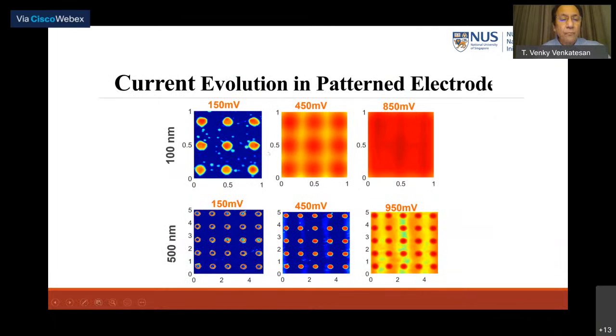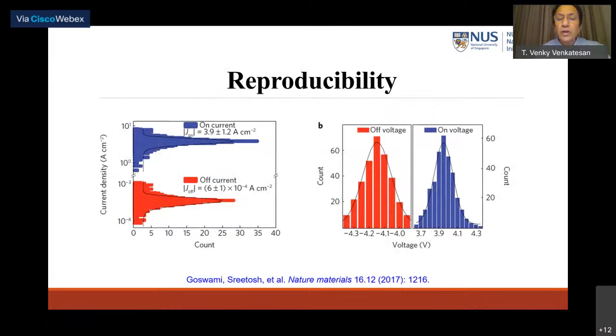Here, for example, are patterned bottom electrodes, and there's molecule everywhere. When we apply a conducting AFM tip and scan over it, you see that by 150 millivolts, this 100 nanometer dot is fully switched, whereas the region in between is not switched at all. What this tells us is that when we make these devices into nanostructures, and right now we've shown that we can get down to a size smaller than 7 nanometers, we'll be able to operate these devices with ultra low voltages, which is very, very exciting. The reproducibility of the device is very remarkable.